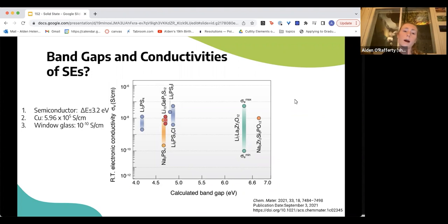So on the y-axis, we have room temperature electronic conductivity in the units Siemens per centimeter. Siemens is inverse ohms. And we see that they have very, very small levels of electronic conductivity. On the high end, these ones are at like 10 to the negative 5. On the low end, they're at 10 to the negative 10, which is not very much conductivity. And again, for reference, something that's very conductive would be copper, for example, and its conductivity is on the order of 10 to the 5th Siemens per centimeter. And something that's not very conductive that you might know is window glass, which is 10 to the negative 10 Siemens per centimeter. So these have large band gaps and are not very conductive, which is what we want.